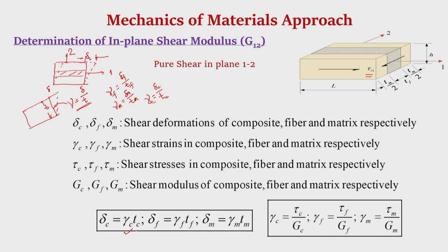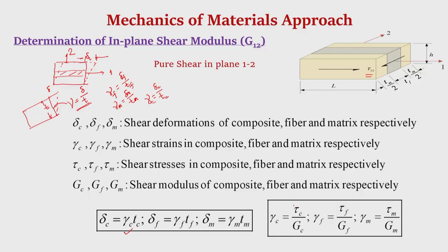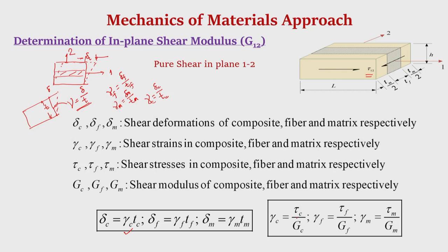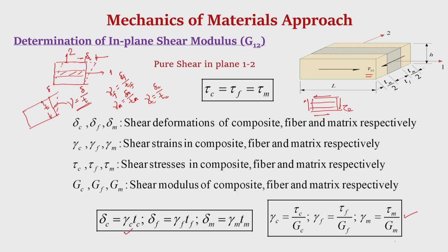Using these relations, shear deformation can be expressed in terms of shear strain and initial thickness. Since the fiber, matrix, and composite are assumed to obey Hooke's law (linearly elastic), stress divided by strain equals the shear modulus: gamma = tau / G. Because the RVE is subjected to pure in-plane shear tau_12, the fiber, matrix, and composite all experience the same shear stress: tau_C = tau_F = tau_M = tau_12.